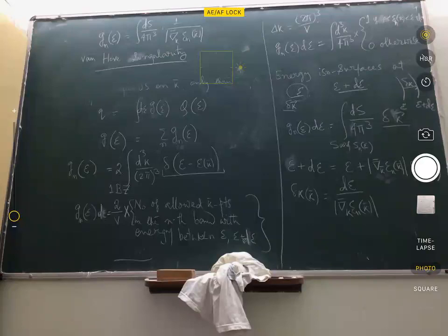So suppose you are supplying energy to that material in the form of photons which have just the right energy. The material would start absorbing energy, and electrons will be excited from the lower energy states to the higher energy states. But there are a large number of states available there, so a large number of electrons can get excited. So there will be a large absorption of the incoming photons or electromagnetic waves, whichever way you look at it. So the absorption coefficient in that energy range would show a spike with some characteristic energy dependence. So these have observable consequences.